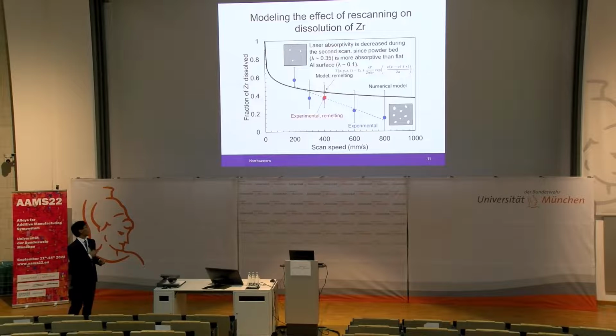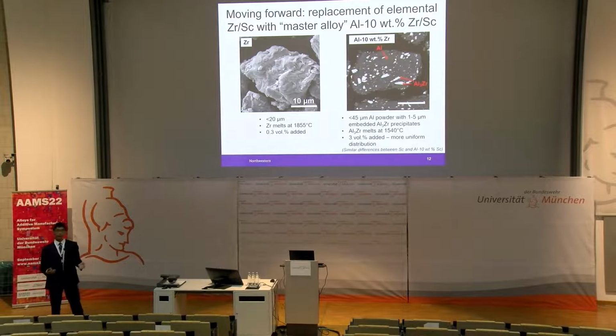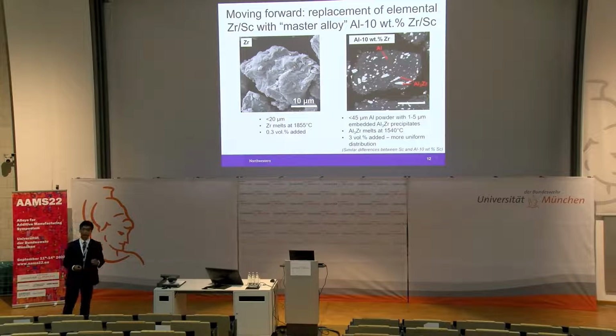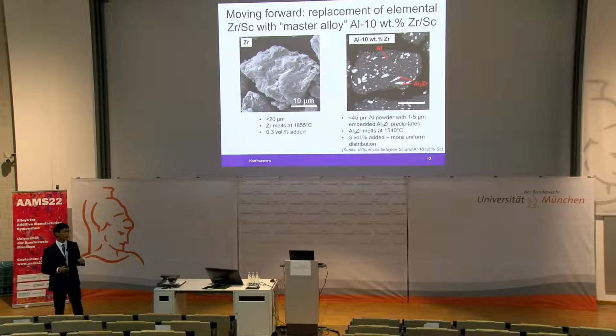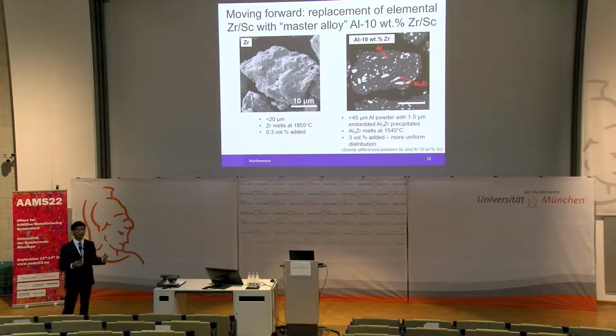Okay, so after all this, what can we now do to affect the microstructural homogeneity further? So of course, if we can decrease the powder size, that should increase the rate of dissolution of these zirconium particles, but also if we can lower the melting point, then we can use a melting mechanism which is faster than the solid state diffusion process. So our choice was to replace these elemental zirconium powders with so-called master alloy aluminum 10% zirconium powders.